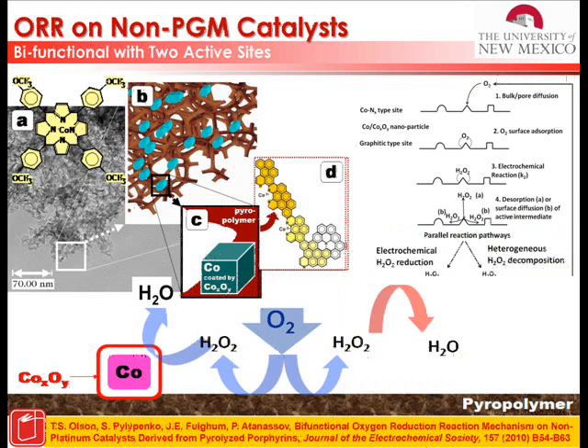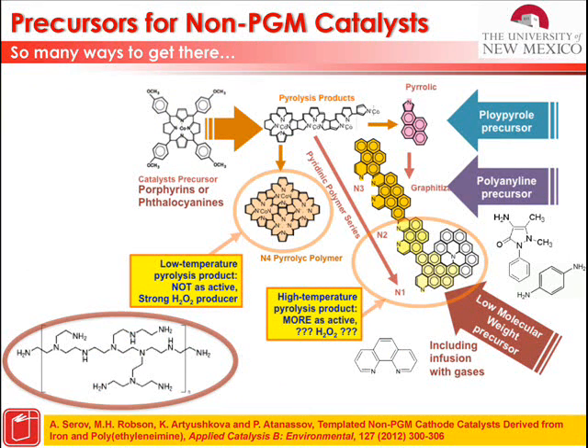And the backbone of the catalyst, which is a pyrolytic polymer that has N3 centers, N2 centers, N centers, and even graphitic nitrogen, all of which are present in the material, presents the first site for the adsorption. And then naturally, there is a third site, which is heterogeneous decomposition of hydrogen peroxide. All these three processes happen. And the question in making a better catalyst is to eliminate this and to make this site do both jobs. And that is what is happening when you design the catalyst further. We have shown that you can start with any nitrogen precursor, porphyrin, a polymer, amine, or heteropolyamine, and you enter this general temperature-time trajectory at different points, and depending on the time-temperature history, you can arrive at a different point of your catalyst structure.